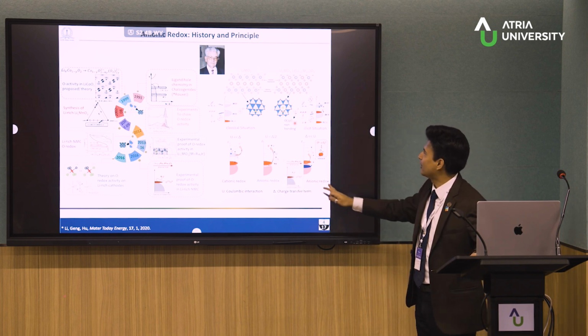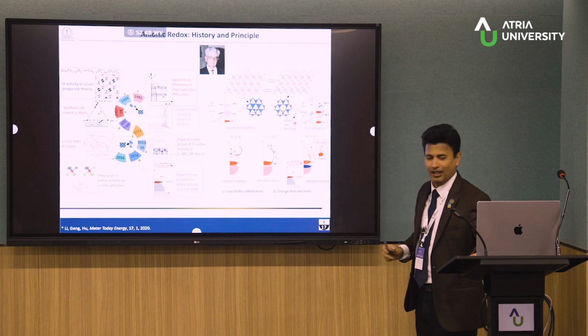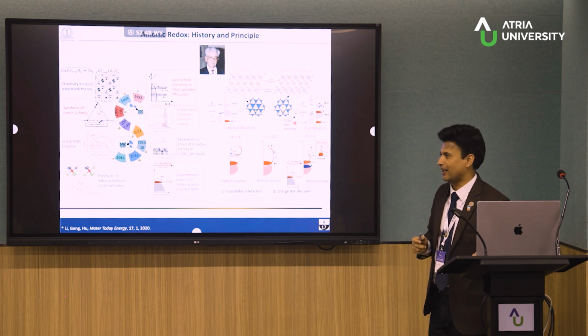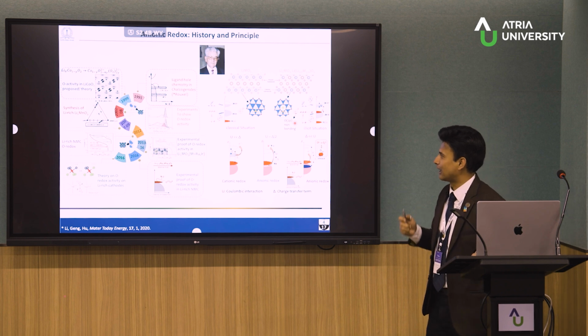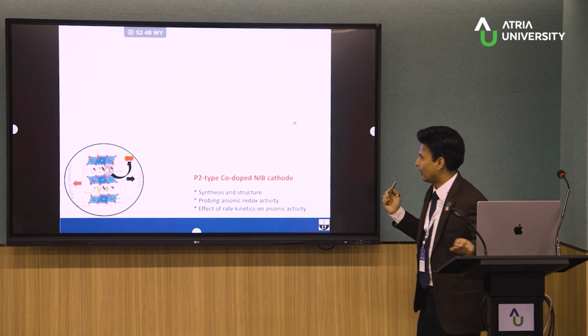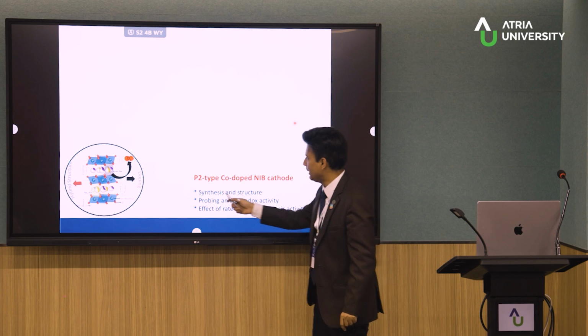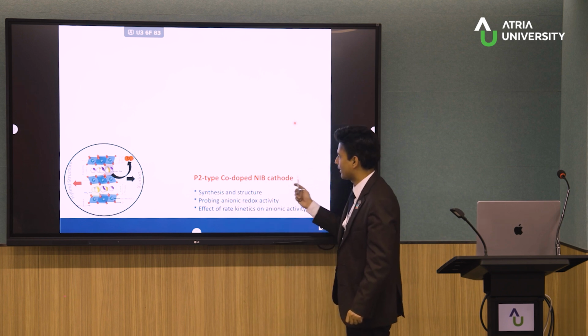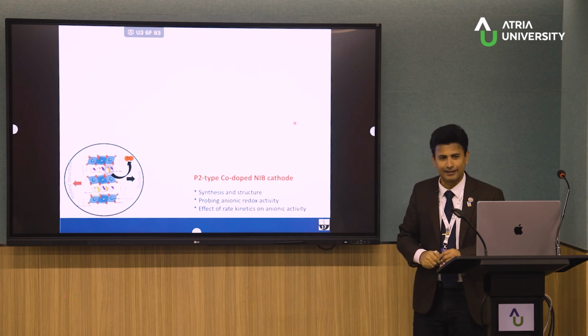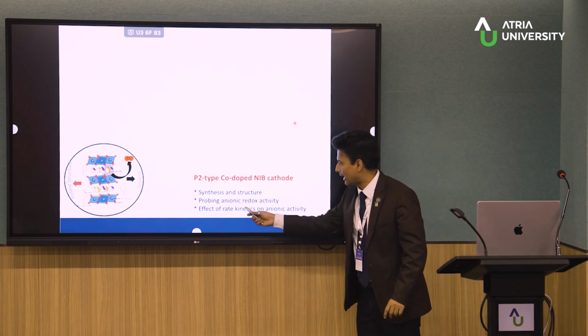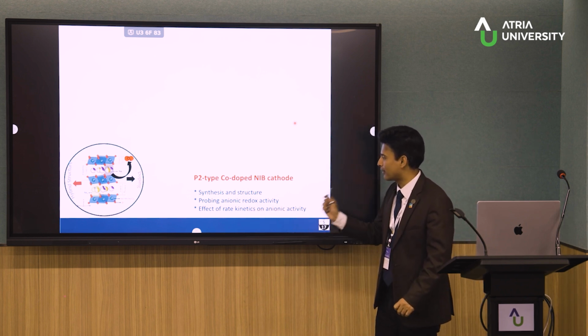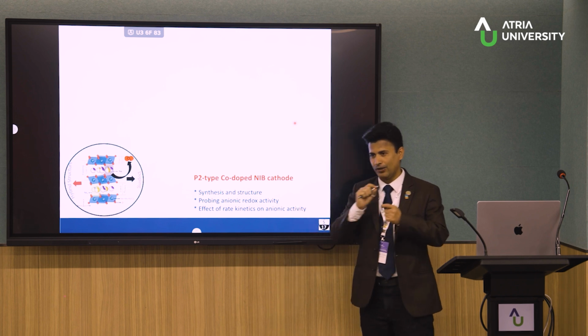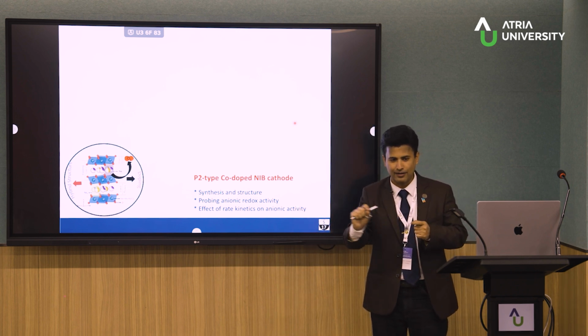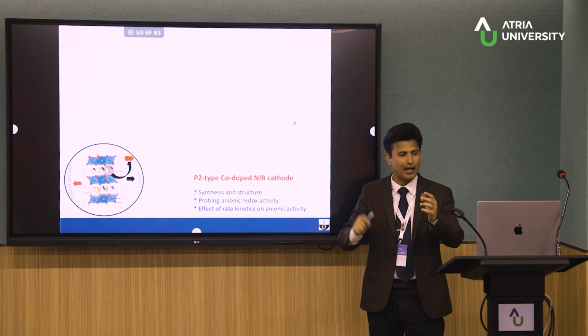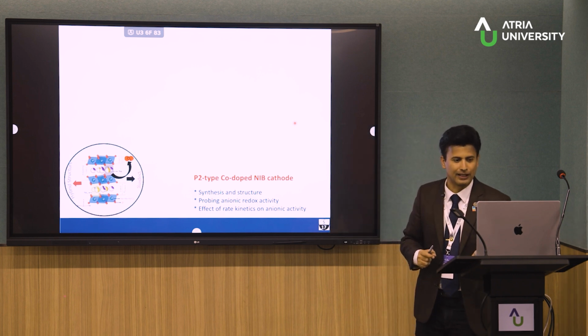So with this kind of basic understanding, I want to show you one classic case study of a sodium-based oxide material for anionic redox. I want to describe one P2-type cobalt-based sodium-ion battery cathode material to discuss its synthesis, crystal structure, and some anionic redox activity and the effect of rate kinetics on the activity. When we charge and discharge very fast, at a moderate rate, or very slow, how does the anionic redox change? I will try to show that.